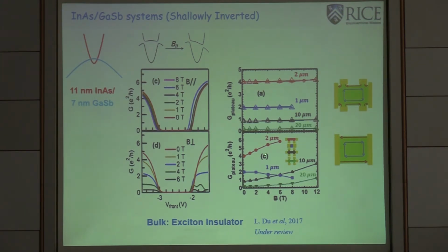Now, if you apply a perpendicular magnetic field, one can find for some samples the conductivity goes up, and for some samples the conductivity goes down. So how do we understand this? Simply because if you have Hall bar geometry, then for two-terminal measurement, you end up measuring the Hall resistance itself. So what you measure is actually the Hall resistance caused by the perpendicular magnetic field.